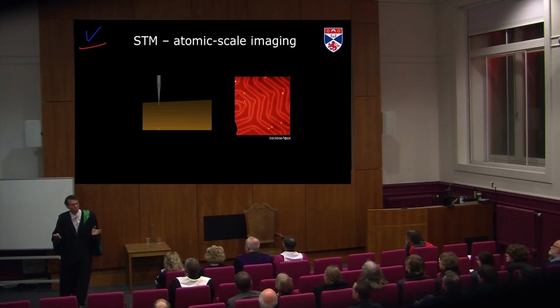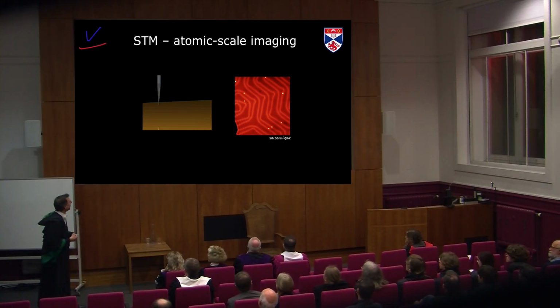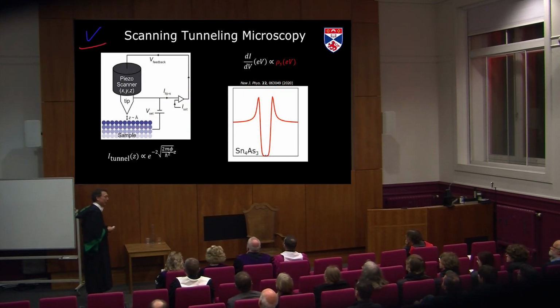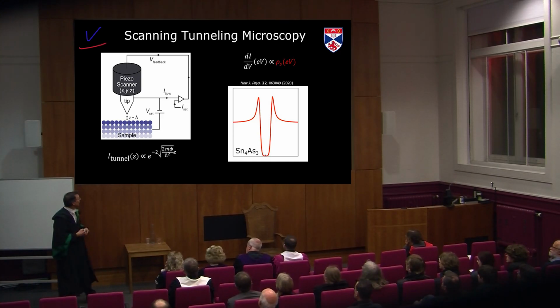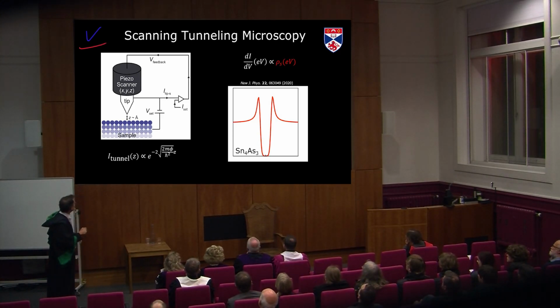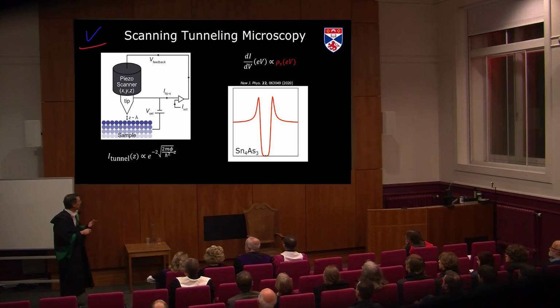Now, these images are nice to look at, but it's actually not the thing we are after. What we really want to do is study the electronic states in the material. And to do that, we have to stabilize the tip at a specific position and then record the current as a function of voltage. So this axis here is the voltage between the tip and the sample. And here it's the differential of the current because that's nicer to look at, but in principle it's the current. And in this case you can see how this differential increases, then drops to 0, and then increases again. So we would say there is a gap in the material. In this specific case, it's actually a superconductor.